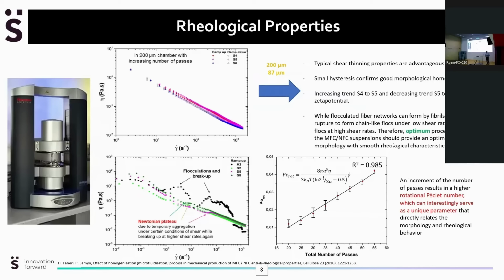And if you look into the rheological properties of such fibrillated structures, they can nicely be related to the morphology of the microfibrillated cellulose. Here, for example, with only homogenizer fibrillation, you see a very slight increase in viscosity from the red to the purple, with increasing fibrillation. But once we go too far into the fibrillation, we see a decrease in viscosity, indicating agglomeration of the fibrils. If you do the rheological scan over a larger shear rate domain, you typically see these characteristics for fibrillated cellulose, with often some Newtonian plateaus, indicating the temporary aggregation of the fibrils and then again the breaking up of these aggregates.